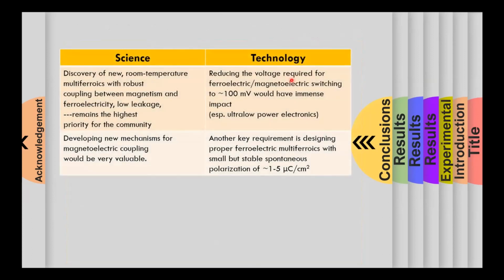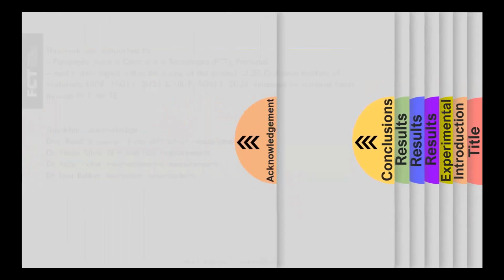And as a general concluding remark, I would like to state that still we need to discover new room temperature multiferroic, which has robust coupling between the magnetism and ferroelectricity. It still remains the highest priority for the scientific community. And we also need to develop some new mechanism for the magnetoelectric coupling. From the technological point of view, one needs to reduce the voltage required for the ferroelectric and magnetoelectric switching to nearly 100 millivolt, because this will have an immense impact, especially for ultra low power electronics. And another key requirement is basically to design proper ferroelectric multiferroics with small but stable spontaneous polarization of around 1 to 5 microcoulomb per centimeter square.